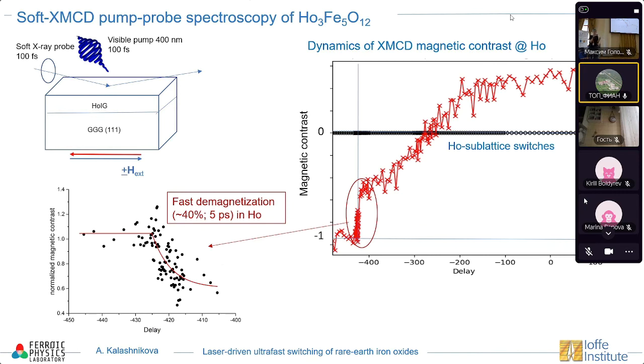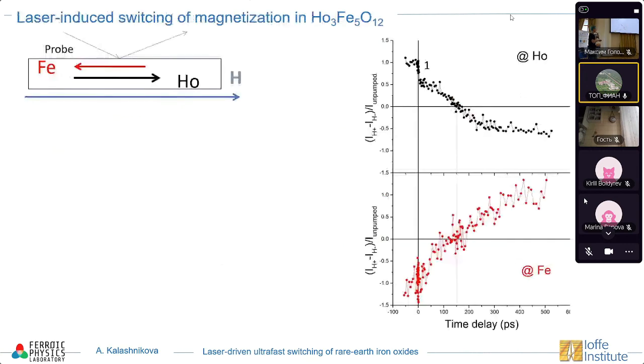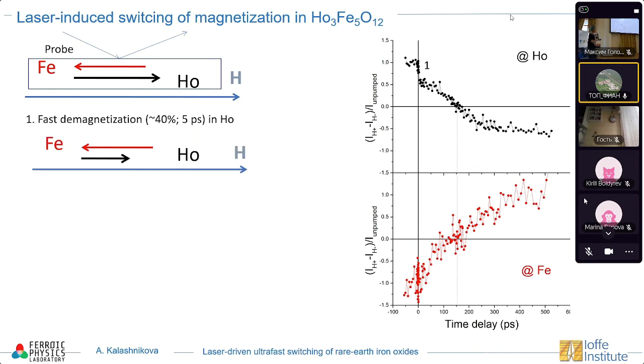So basically, when we excite the material with a femtosecond laser pulse, the magnetization of holmium drops very fast, on the time scale of several picoseconds, while the magnetization of iron doesn't really change at this time scale. Here the contrast at holmium and at iron is plotted together, and we suggest the following scenario for switching. First, we have ultrafast demagnetization in holmium. Before the excitation, the holmium magnetic moment was larger, therefore the holmium moments were along the magnetic field, and iron was opposite to the field. Then 40% demagnetization of holmium happens, and clearly this is no longer a stable situation, because now the net magnetic moment is pointing that way, against the magnetic field.